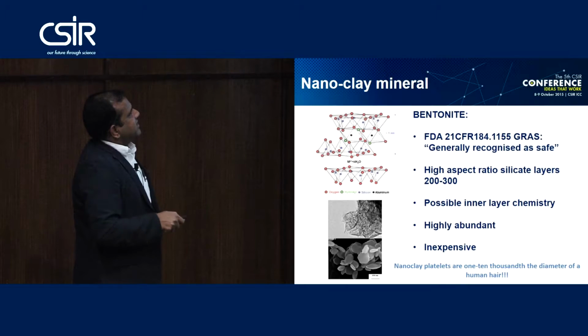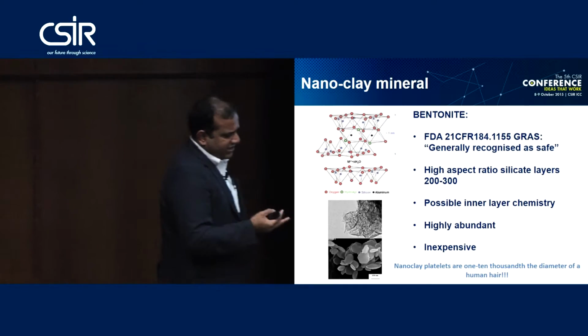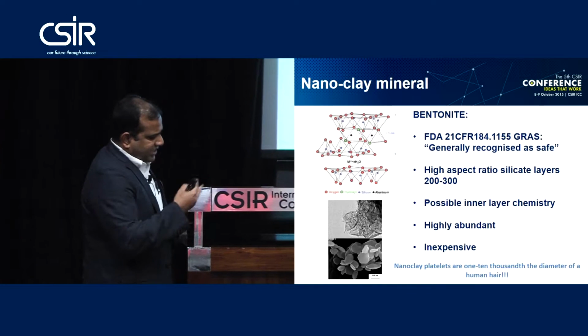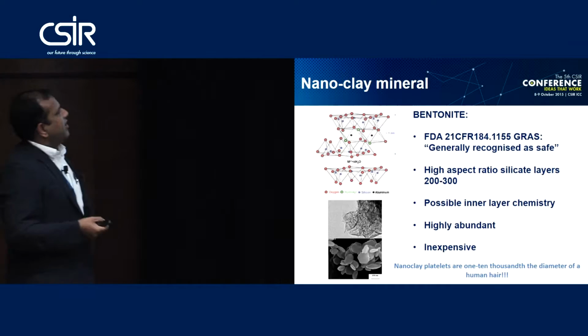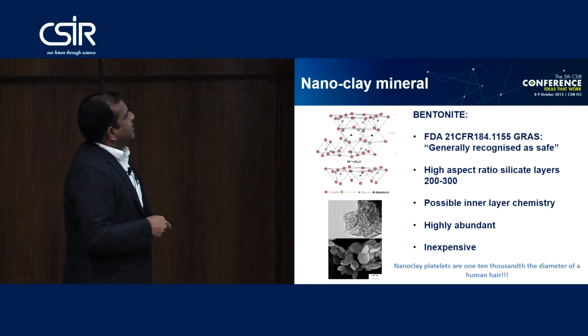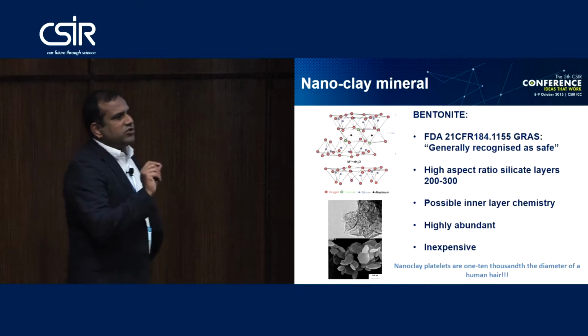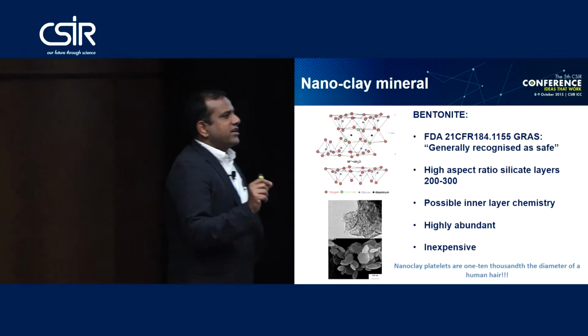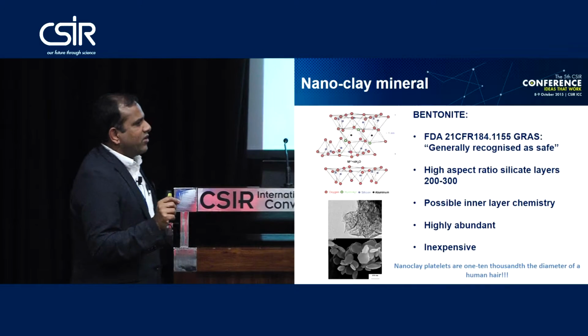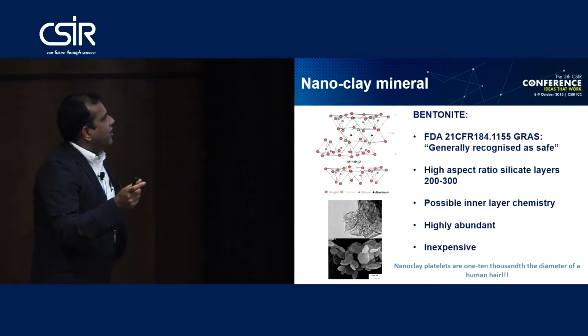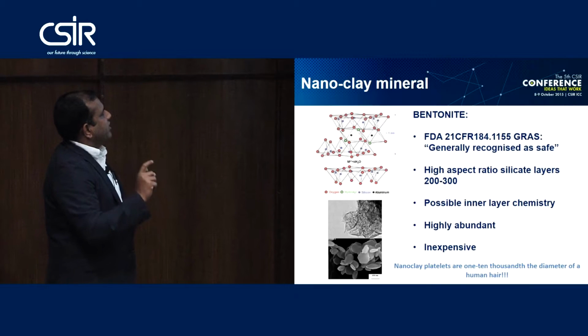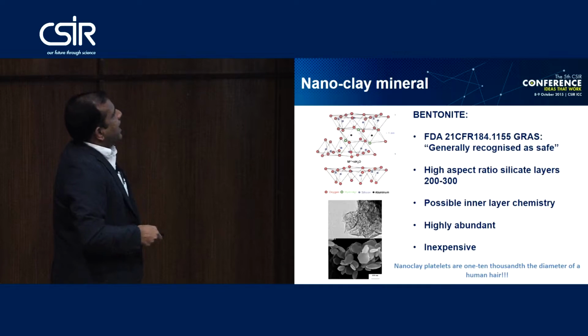And why we are very interested for mostly commodity applications is because this is already considered by the FDA as generally recognized as safe. I think all of you know that for a long time we have been using clay in a number of products, particularly in the medical field. Then it also has a huge high aspect ratio, because that is the most important part when you want to use nanostructure materials to improve mechanical properties, because you need that kind of transfer of stress between the filler and matrix and matrix and filler. And also possible polymer interlayer chemistry, that I will come back to shortly.